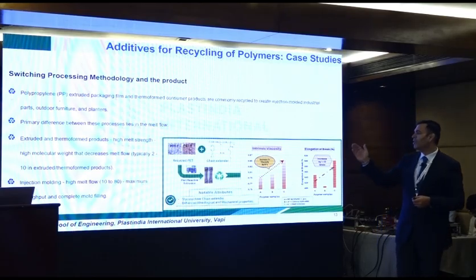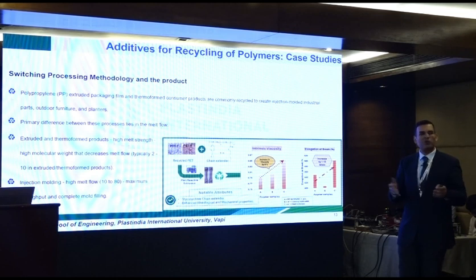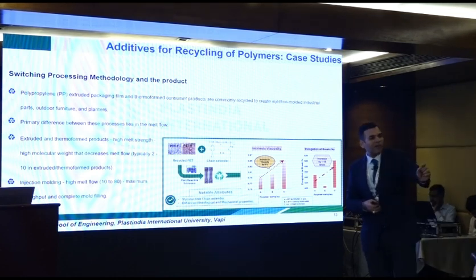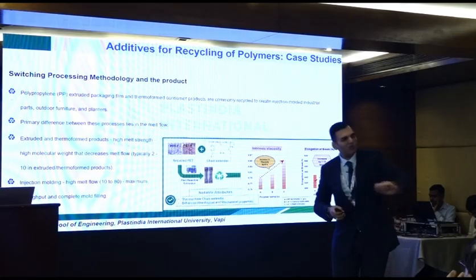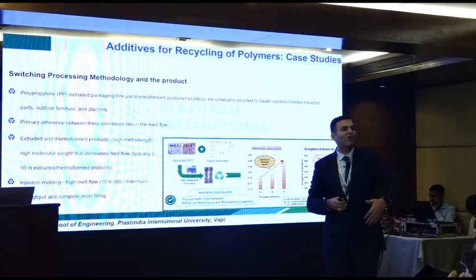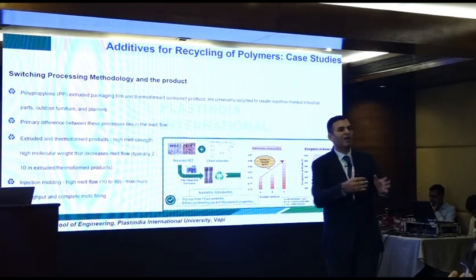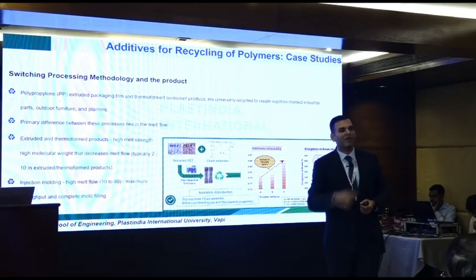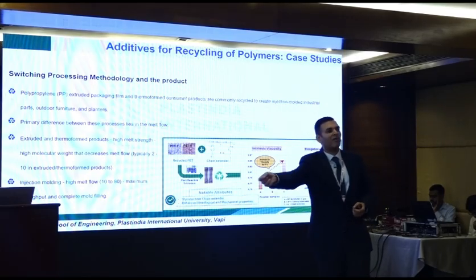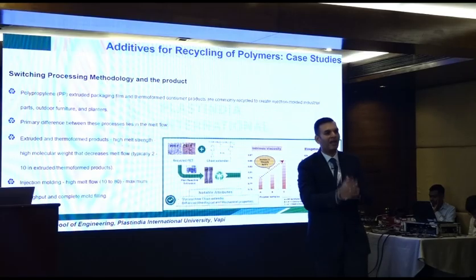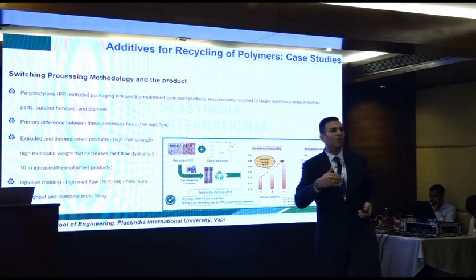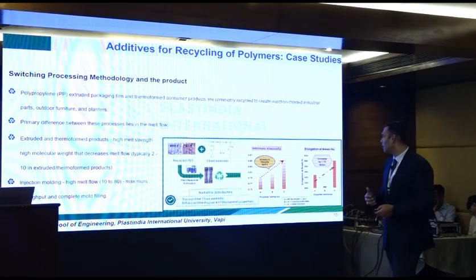And injection molding, we are talking about high melt flow, can be 10 to roughly 50, 55 or 60, which requires मेरा 0.5 mm का कोई recess है, the material should flow inside. ऐसा नहीं होना चाहिए कि cold well आ गया, material freeze हो गया, या कहीं पे मटेरियल फ्लो करते करते ऑब्वियसली temperature नोजल से जिस temperature पे निकला था, मोल्ड का temperature काफ़ी कम है, सो temperature नीचे गिर रहा है और वहाँ तक पहुँचते पहुँचते या वहाँ फिलिंग करने के पहले you have your mold, the channel has cooled off, right? So you will not be able to flow the material.